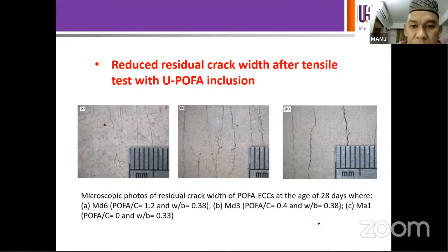So reduce residual crack width after tensile test with UPOFA inclusion. The last one, C, is the control without the POFA, while B is having POFA over cement of 0.4, and A is having POFA over cement of 1.2 in terms of ratio. So we are seeing much finer cracks, but with a greater amount of cracks, in the case of ECC containing the higher amount of POFA.